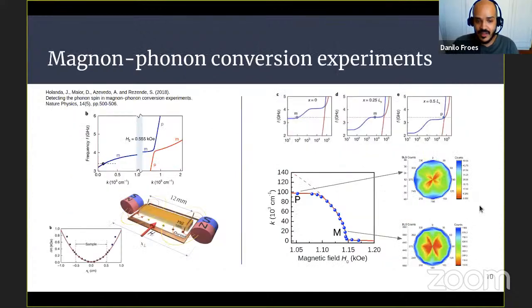And finally, this work from 2018 from Holanda and Sergio Resende's group. Not only can we couple these magnon and phonon states, we can also make conversion between magnon and phonon states. And here's what they've shown. This was the first case we were collaborating with this group. So using the two branch separations, the anti-crossing between the two branches here, by making use of a non-uniform magnetic field, so a spatially varying magnetic field, the dispersion curve changes with the position.